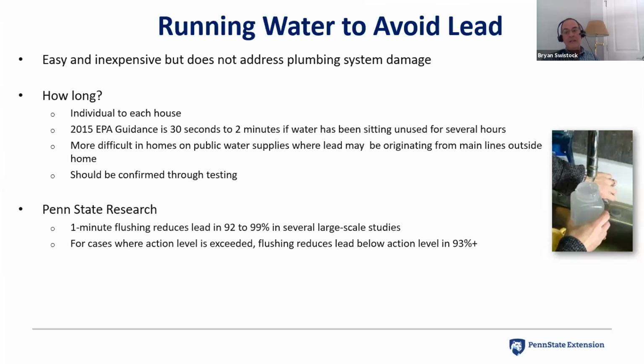And what we have found in our research is that 1 minute of flushing reduced the lead concentration in 92 to 99% of the cases, depending on which study we look at. It's been anywhere between 92 and 99% of lead levels reduced just based on 1 minute of flushing by private water system owners. If you just look at people that have lead above 15 parts per billion and separate them out and look at what's the effect of flushing the lines for those people, in our research, it's been about 93 to 95% of those cases can be reduced down below the action level.